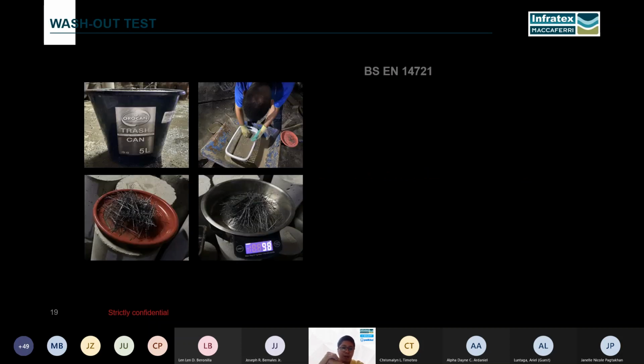After checking the slump, we'll be doing a washout test. The washout test is to determine whether we have the right amount of fiber per cubic meter. This is based on British standard EN 14721. We take 3 samples into a 5-liter bucket, then separate the fibers from the concrete mix. We separate them by vibration, washing out the mixture, then picking out the steel fibers and washing them again. Then the collected fibers will be weighed and the allowable result must be within the range of plus or minus 10% to allow it for pouring.